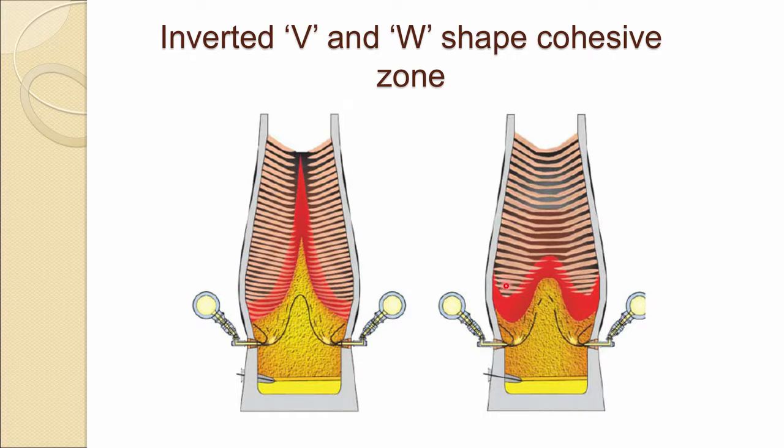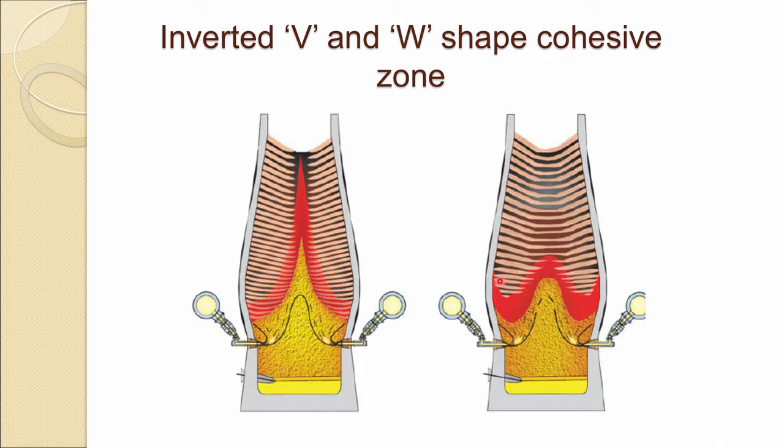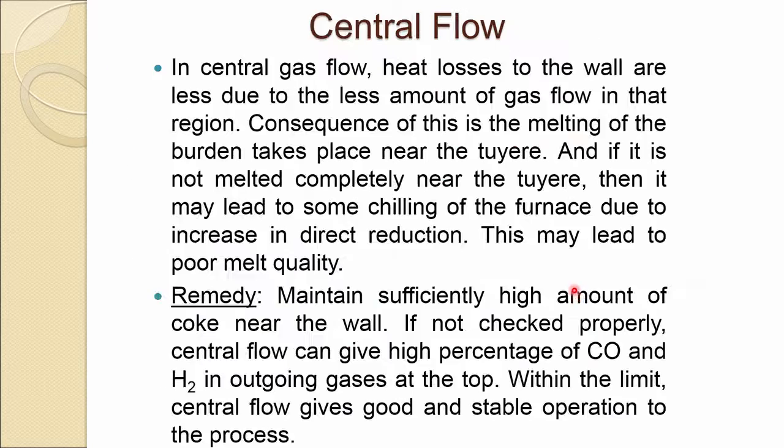If it gets disturbed, then gas cannot flow from here, because this is the only material which is solid now and has also voidage, a good amount of voidage, about 50% or 0.51 as you have seen it. So, most of the gases, they are passing through this coke slit now. So, this zone is very important to maintain the viscosity, the melting point, softening melting point, and we are talking about that.